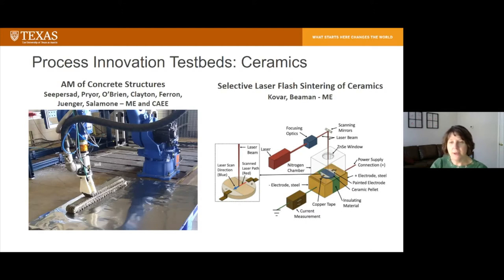So instead what they're working on here is a novel new process that combines an electric field with a scanning laser. And the idea here is that you can lower the temperature and greatly increase the speed of direct laser sintering. And then from that we can achieve green parts that we can later sinter fully in an oven.